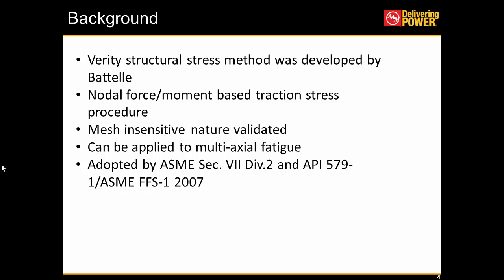So the Verity module in FE-Safe is able to calculate the structural stress which was developed by Battelle. Compared to the extrapolated stress-related approaches, it uses nodal forces and moments to calculate a traction stress component. Because of this, it's generally mesh insensitive as long as we are able to represent the geometry well. And it has been validated for different geometries, different programs, and different sizes. This mesh insensitivity is especially useful for us because we have full axle components, which can have millions of elements and 50 to 100 welds. And the usual process can be really time consuming.